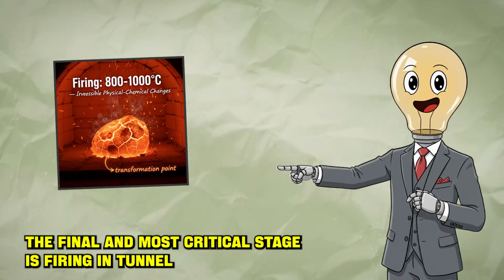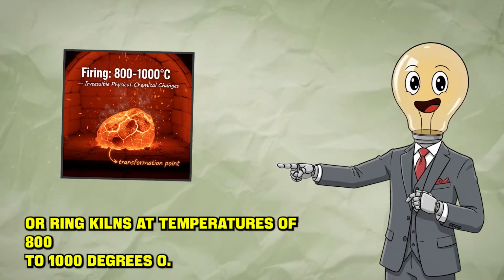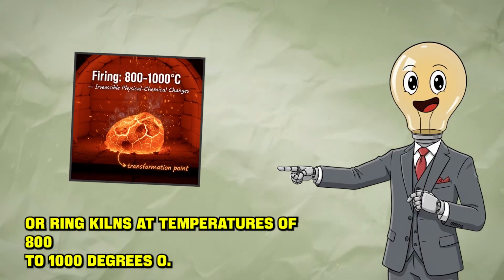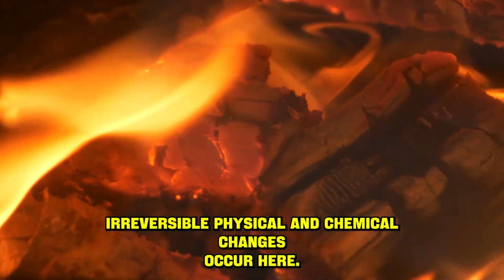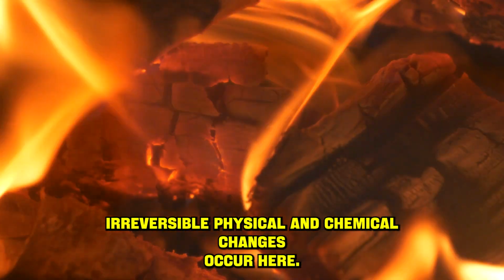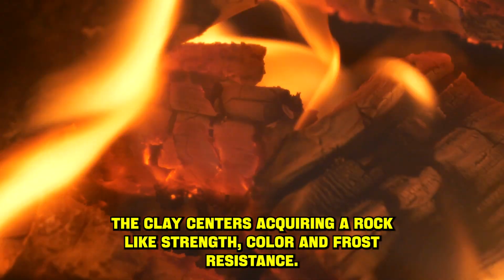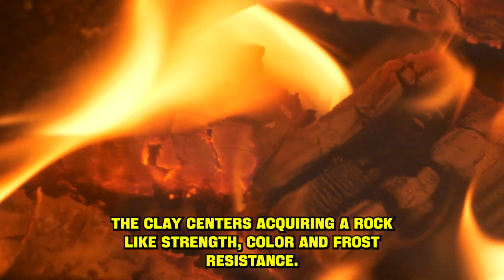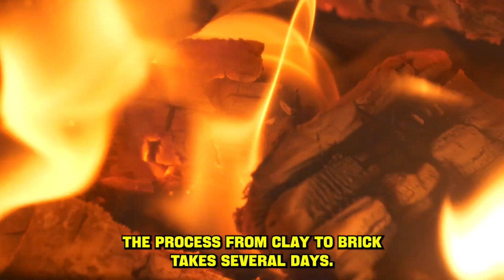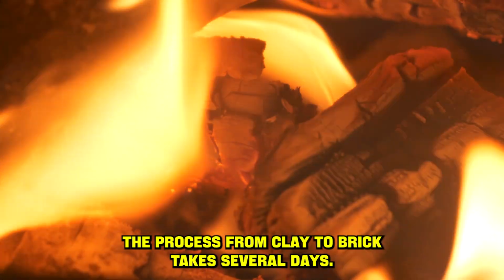The final and most critical stage is firing in tunnel or ring kilns at temperatures of 800 to 1000 degrees. Irreversible physical and chemical changes occur here. The clay sinters, acquiring a rock-like strength, color, and frost resistance. The process from clay to brick takes several days.